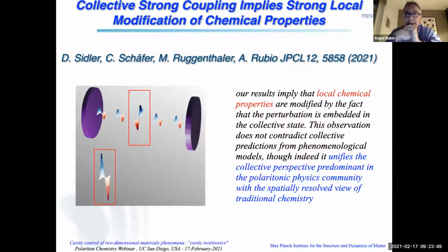And then as you realize, what I did is basically take a single molecule or two molecules. One of the beauties of this system, and that has been introduced, is the fact of using the collectivity of having n molecules in the cavity which do not overlap and interact weakly among themselves, and then use that as a way to enhance this lower and upper polariton separation and call it strong light-matter coupling. I would like that this concept is still there. There is this, as you saw before, lower and upper polariton splitting.